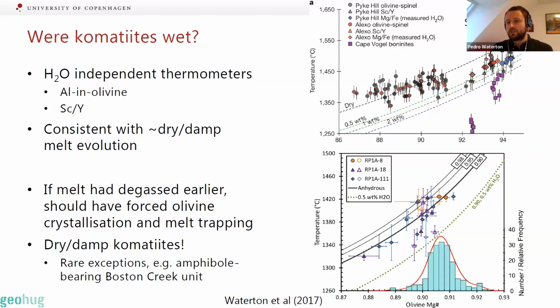And the top one from Sobolev et al. 2016, I think is particularly good because they show a comparison to boninites that we know are wet. And you can see that in the boninites, which are these purple squares, the temperature falls more rapidly with the forsterite content. This is just because as olivine is crystallizing, the water is increasing in the melt. But in komatiites, by comparison, we start off with a little bit of water, in this case about 0.5%, 0.6%. And as this degasses, you end up on a dry melting trend.